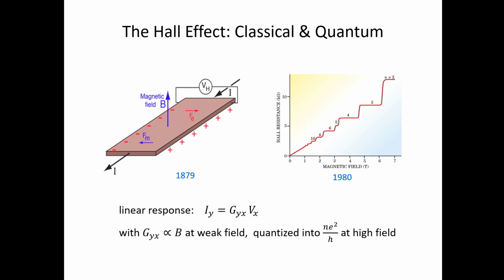in the linear response regime, and this occurs by the name of the so-called Hall effect, and that always requires either an external magnetic field or magnetism that breaks time reversal symmetry. The classical Hall effect was applying a magnetic field in the z direction, passing current in the x direction, there will be voltage in the y direction, and this Hall conductance is linearly proportional to the magnetic field, which is a very, very small effect in conductance.